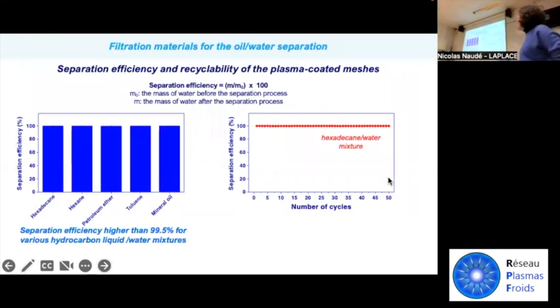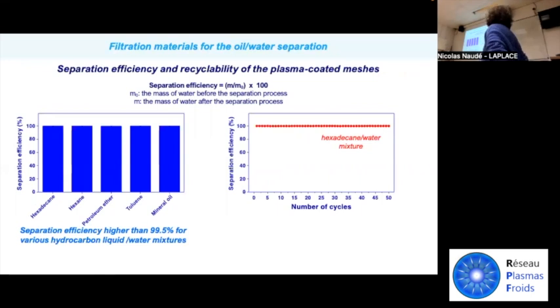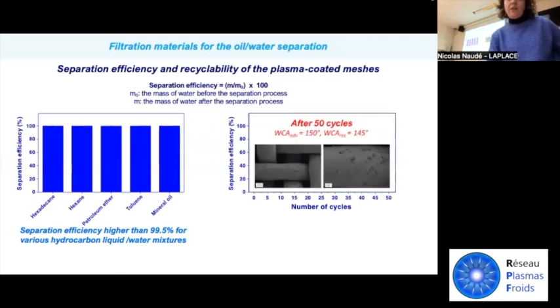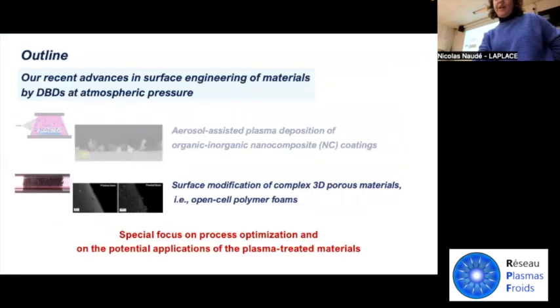A good separation efficiency was obtained with several hydrocarbon solvents and hydrocarbon mixtures. And we obtained a good recyclability of the plasma-coated mesh. That is, after 50 cycles of separation, the separation efficiency is greater than 99%, and also the advancing and receding contact angles are almost unchanged. So the superhydrophobicity is maintained.